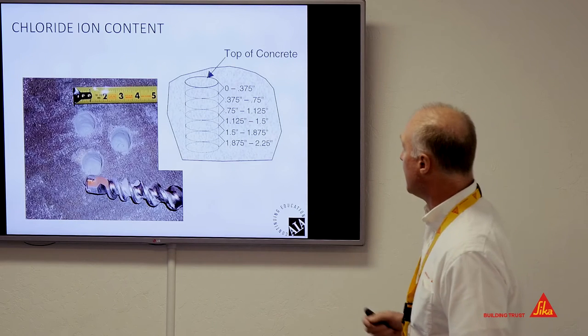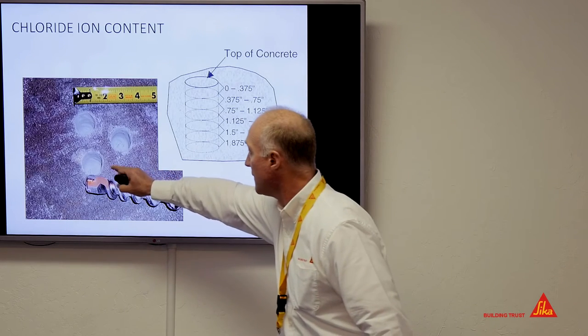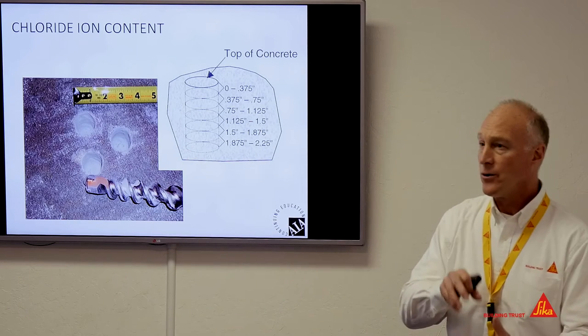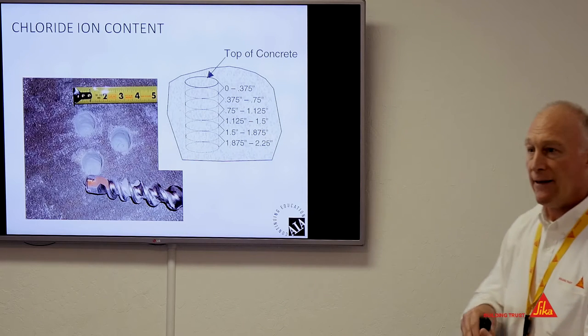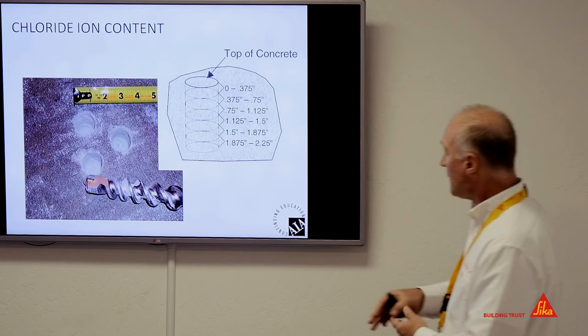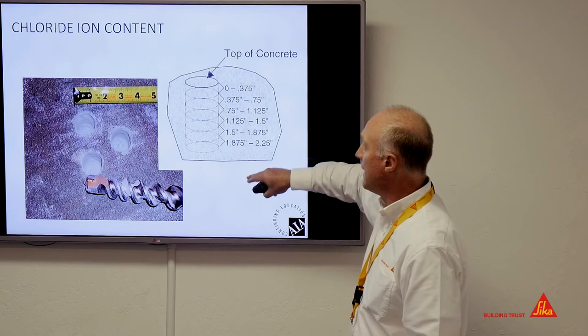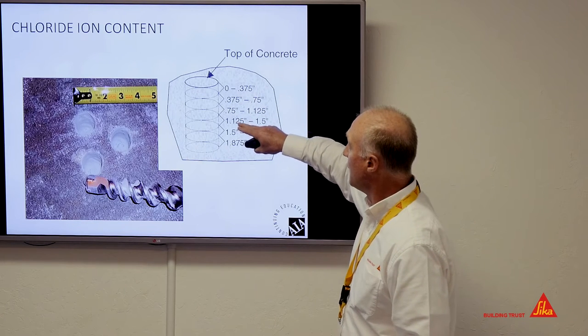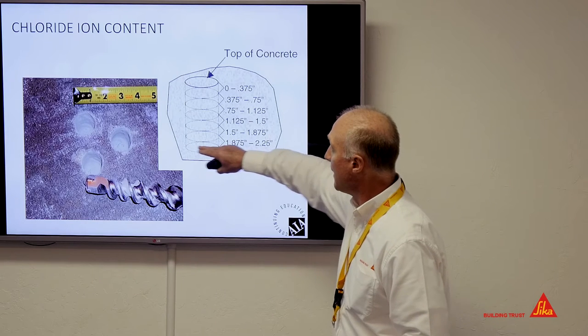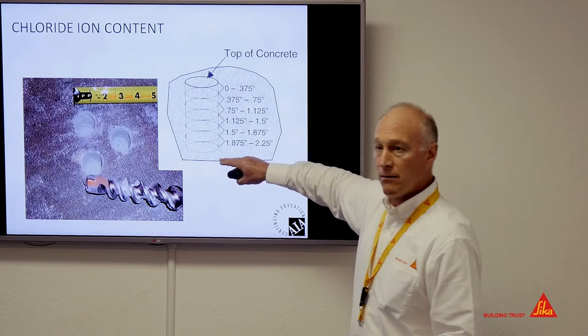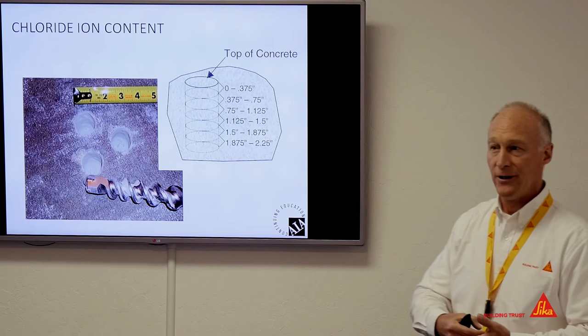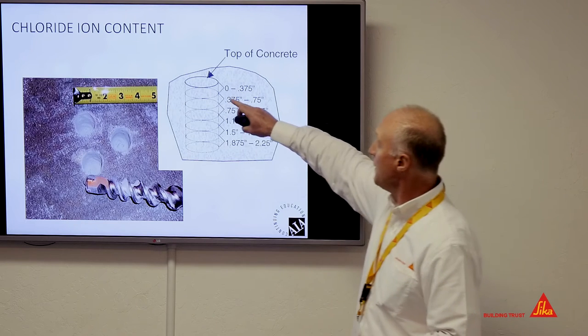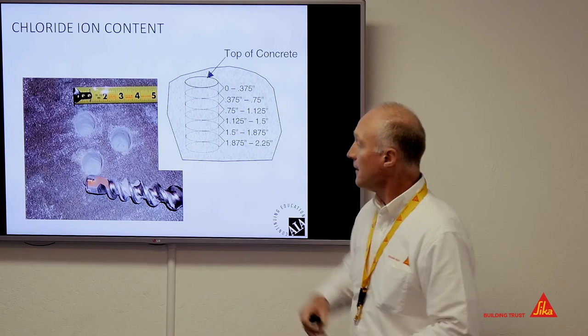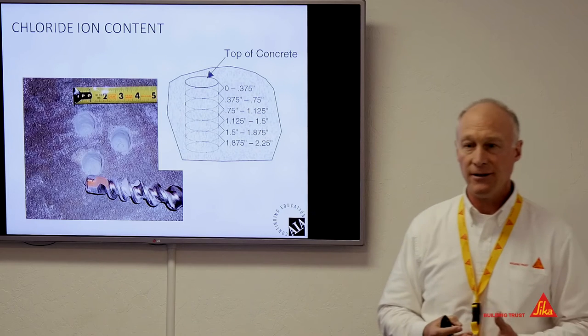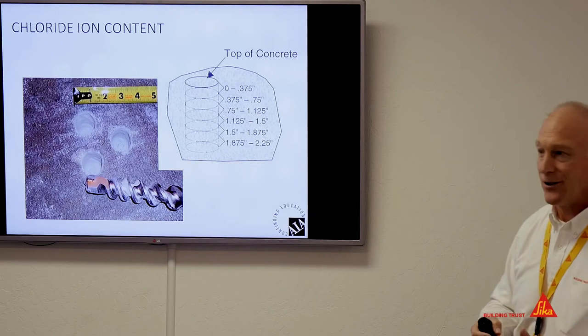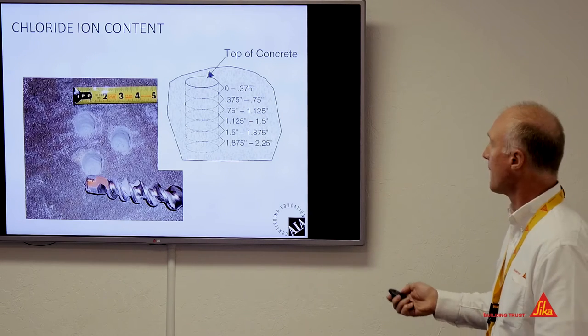So for chloride content, still a common ASTM test, they'll drill a few holes, pull out the powder, and then test it for chlorides. And they'll often test it at different depths. The idea is if I've got good cover and my rebar is down here, more likely my chloride levels are going to be lower at that point. If my rebar is up here, it's going to be in a higher chloride condition because it's going to take less time to get to the steel because it's closer to the surface.